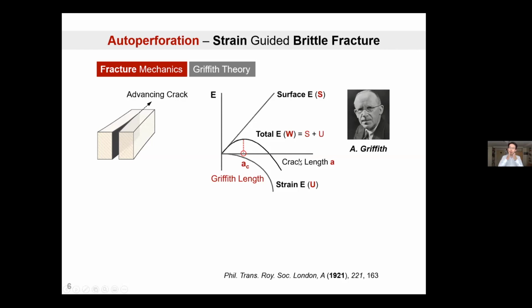At the same time, when breaking the material, the strain energy that is built up within the material will necessarily drop precipitously. So if you sum up these two contributions to the total energy, you get this concave shape, with the vertex of the concave being this critical length scale that we call the Griffith length. This is interesting because the theory predicts that any crack shorter than this Griffith length, on the left-hand side of it, will not grow, because further increase in the crack will increase system energy. On the other hand, if your crack length is on the right-hand side of the Griffith length, it will precipitously grow and the material will fail.